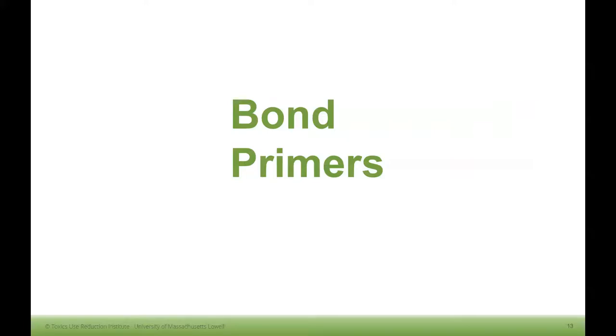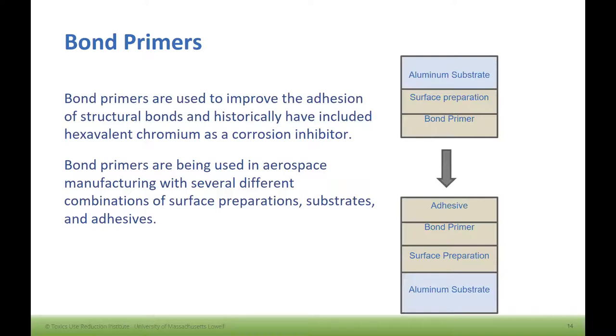The next application we'll talk about is bond primers. You use bond primers when you need a structural bond between two metal substrates, and again, we're just talking about aluminum substrates. You would do some type of surface preparation on the substrate, then apply the bond primer on both substrates. Then you would apply an adhesive and put the substrates together to make a structural bond.